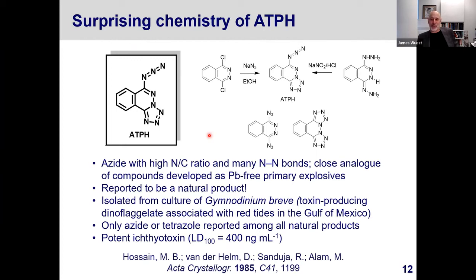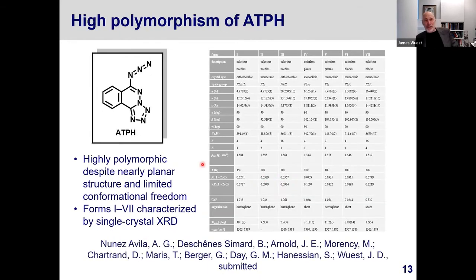An organic chemist who sees this in the Dictionary of Natural Products would say, where in the world did this come from? It is definitely an effective poison for fish. The 100% lethal dose is only 400 nanograms per milliliter. So there seems to be some connection with the interest of this compound as a toxin. Now, the other thing that's interesting, and it was totally unexpected when we began to examine ATPH, is the fact that the compound is highly polymorphic.